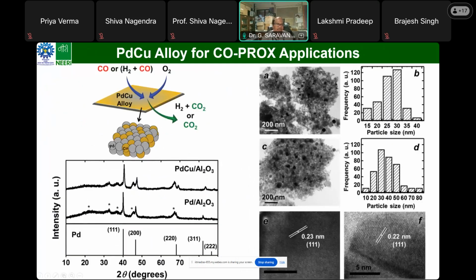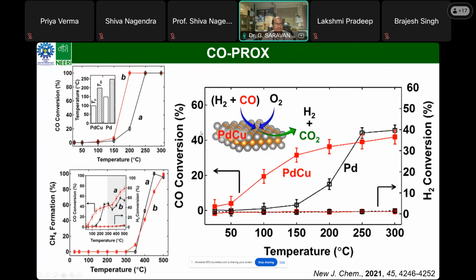Completely platinum free, here we selected an intermediate alloy phase of PdCu that we prepared for the same application. It again has important potential to selectively remove CO from the hydrogen-rich stream to CO2. In the alloy phase, it shows much better activity even at very low temperature. The energy penalty is much lower in this case than pure palladium. So achieving an alloy or intermetallic phase is promising for these applications.